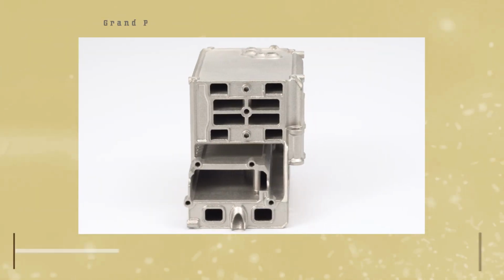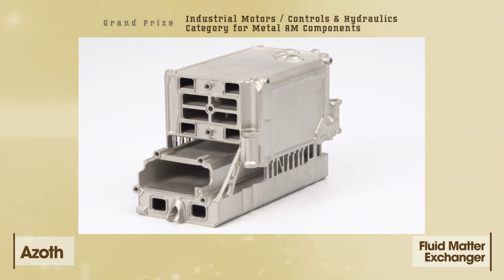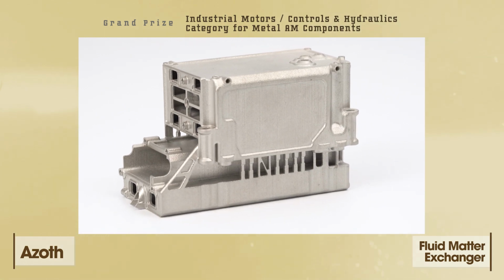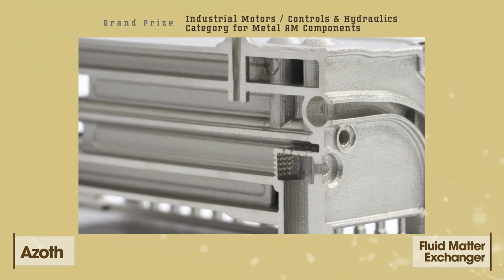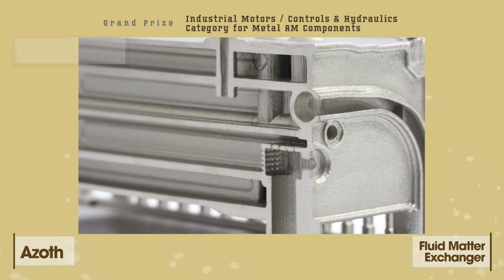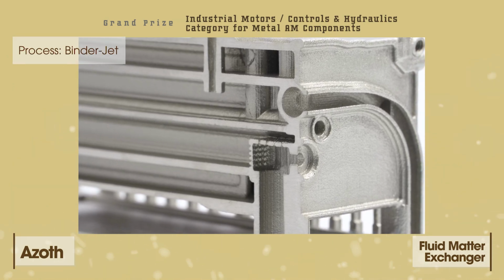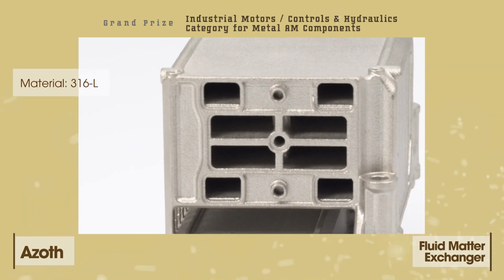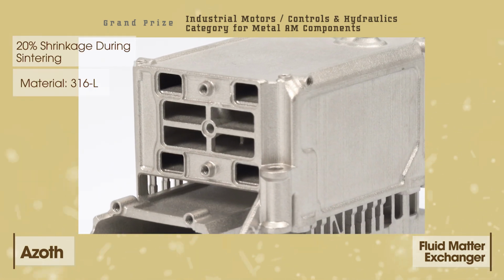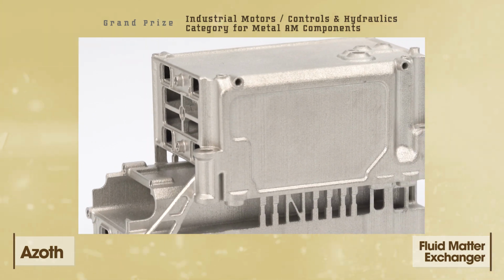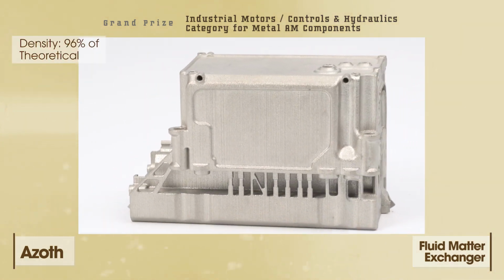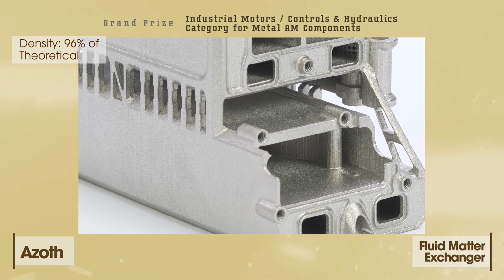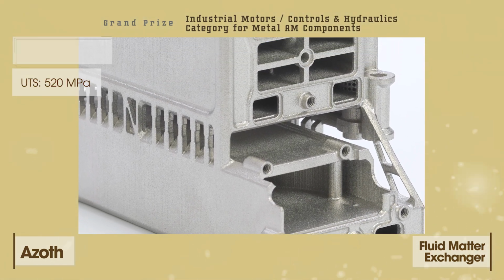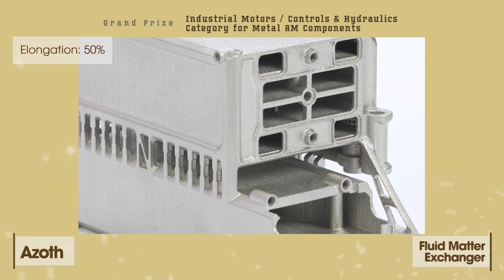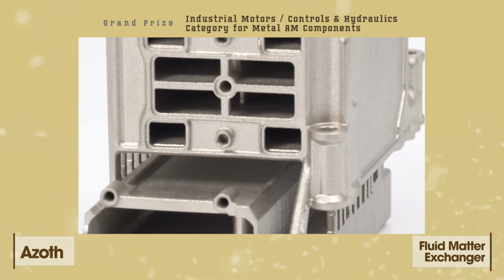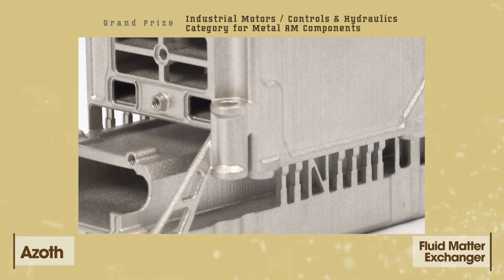Azoth received a grand prize in the industrial motors, controls, and hydraulics category for metal AM components for a fluid matter exchanger. While relatively simple in appearance on the outside, this fluid matter exchanger is extremely complex on the inside. The part is binder jet processed using 316L stainless steel powder, and the as-printed part is about 20% larger to account for shrinkage during sintering. Live setters are printed right underneath each part in the build box. The live setters are designed to fit the complex bottom of the part and allow the part to be sintered vertically. Additional printing enhancers are printed within the build box to facilitate the depowdering operations.